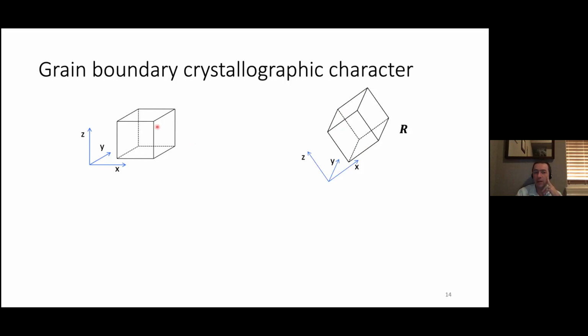boundary. The way we describe this difference in orientation is by describing the relative rotation, the rotation that you would have to apply in order to rotate the grain on the left into the configuration on the right. We can do that by giving a rotation matrix, R. There are other ways to describe rotations as well. However, no matter what approach you choose to describe this relative rotation, the number of independent parameters that you need to specify that rotation is always 3.